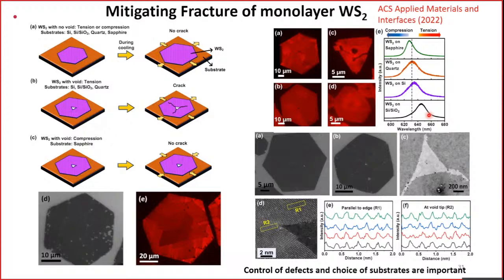So when you try to grow WS2 on Si/SiO2, it is very easy to get fractured because there is a huge amount of thermal mismatch stress. Especially, the nature of the stress is tension, whereas on sapphire you will have compression. In compression, you will not have a fracture. If at all, some buckling may take place.